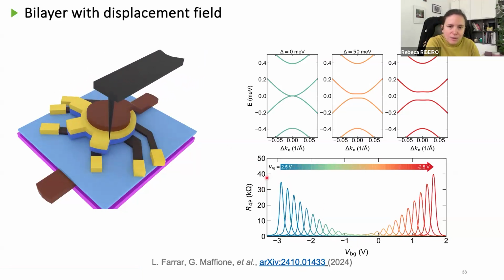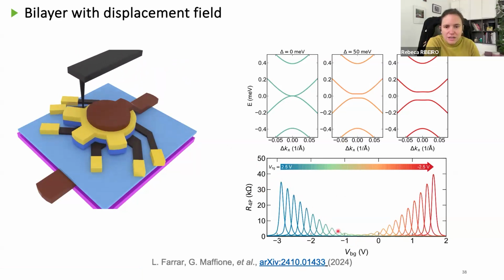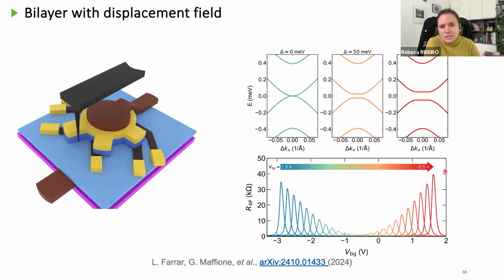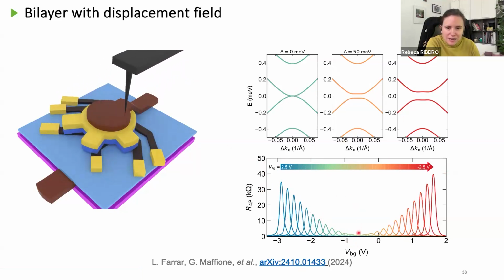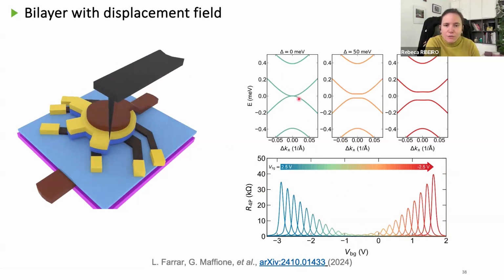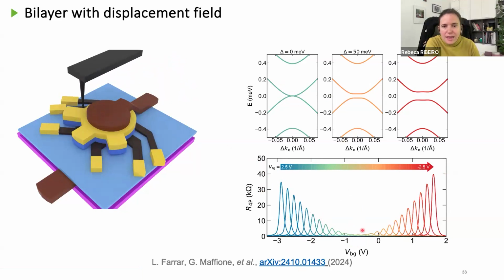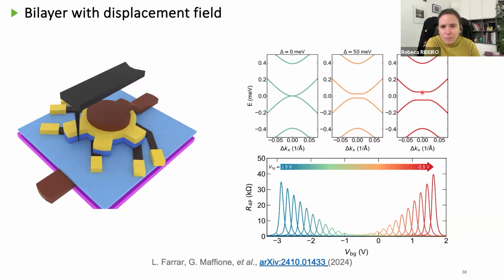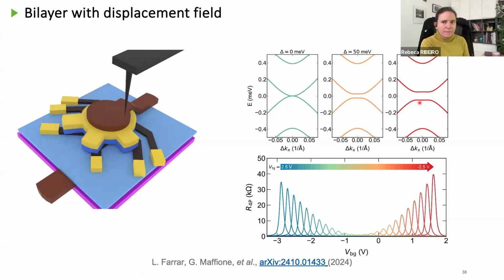And you can see that we have a strong increase of the resistance, and then a strong decrease and a strong increase. Which means here in the middle, we have a fully closed energy gap. And as we go in one sense or the other, we have the opening of this energy gap.